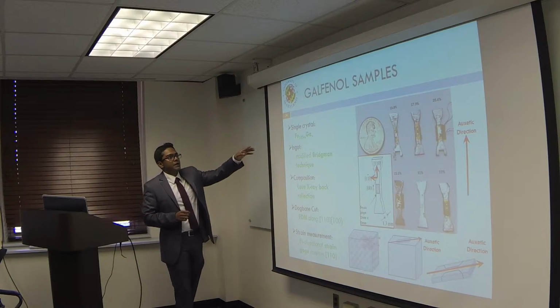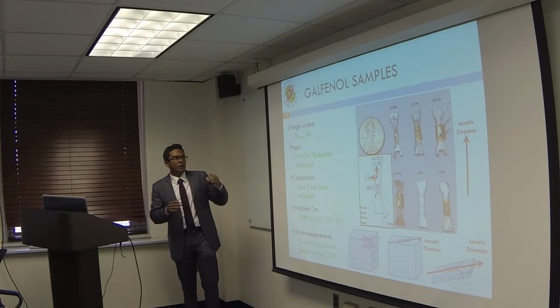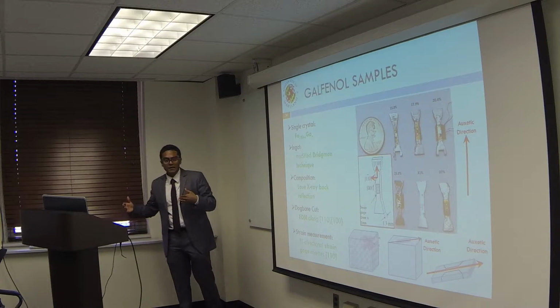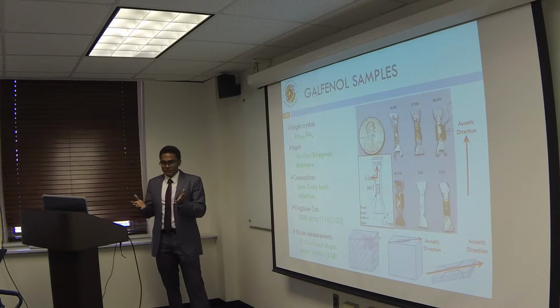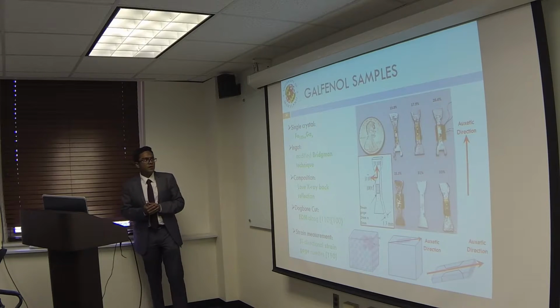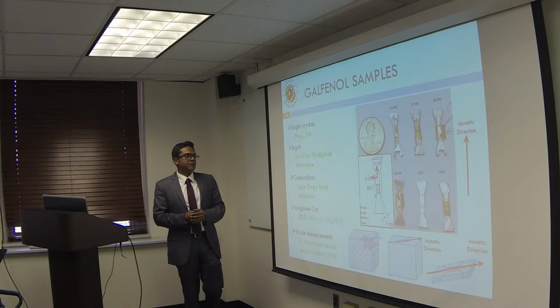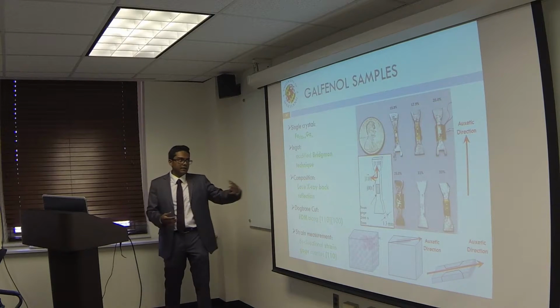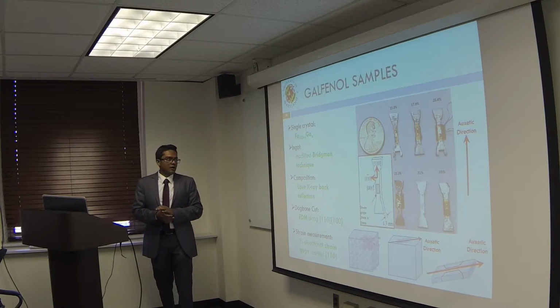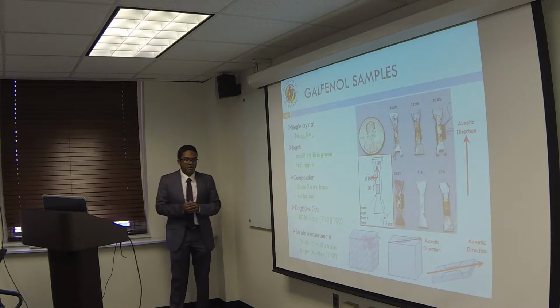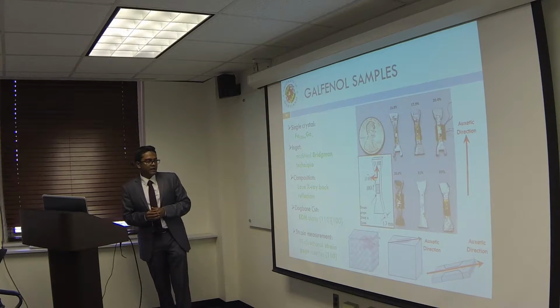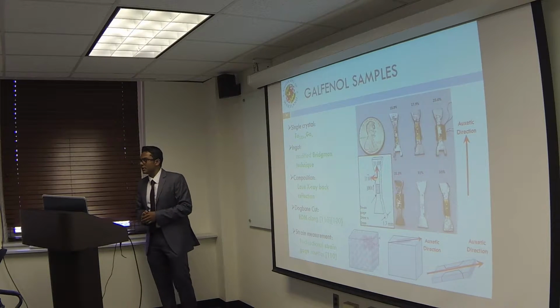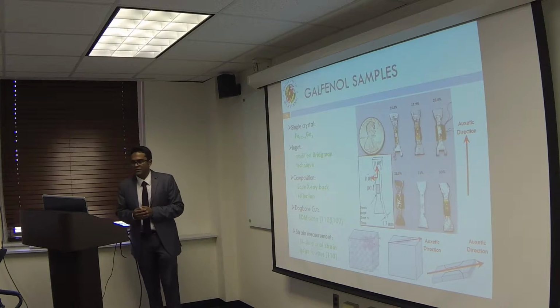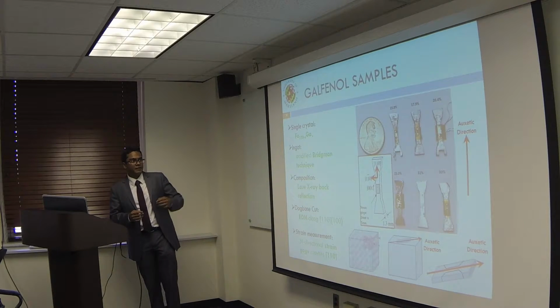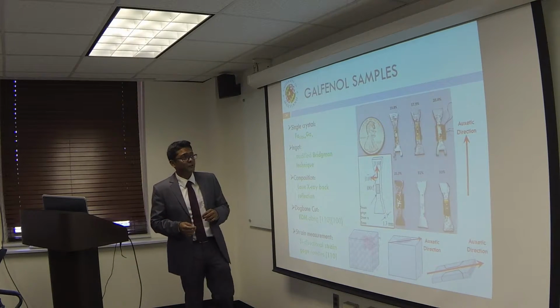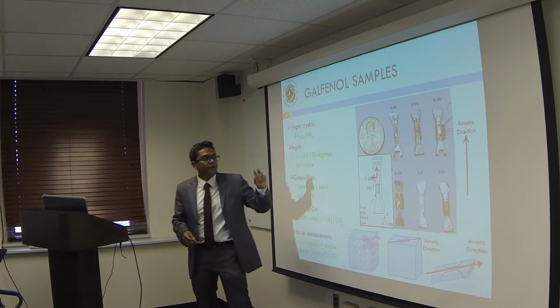So we decided to use single crystal samples of Galfenol with compositions between 12 and 33% gallium. We got the samples from Ames Lab in Iowa, and they built the samples using a modified Bridgman technique. Once the ingots got here, we checked the composition using Laue X-ray back reflection. Then we cut the dog bones using the wire EDM technique, and then we installed bidirectional strain gauges on the dog bones, and we put them between the pole pieces of an electromagnet, and we varied the magnetic field.